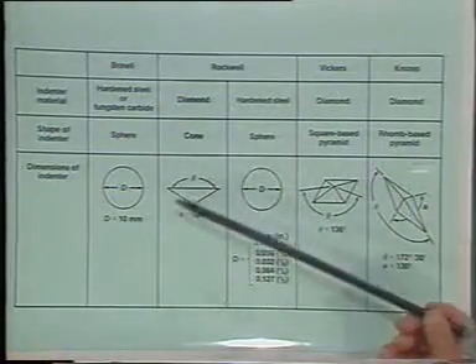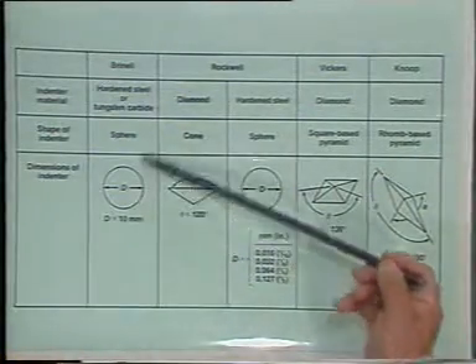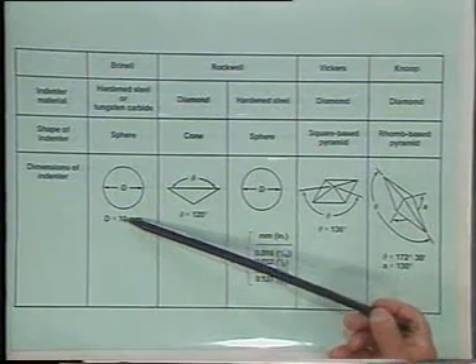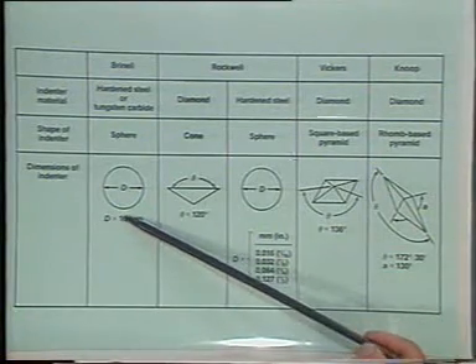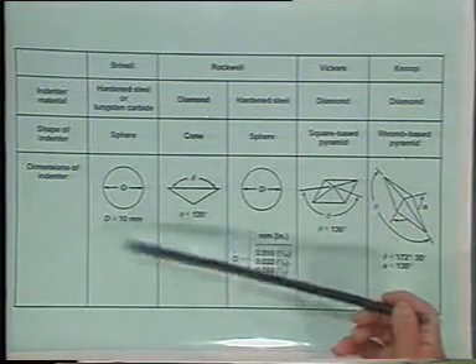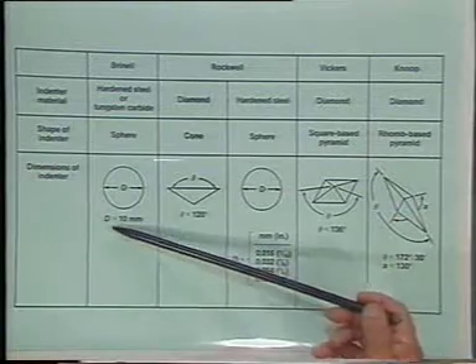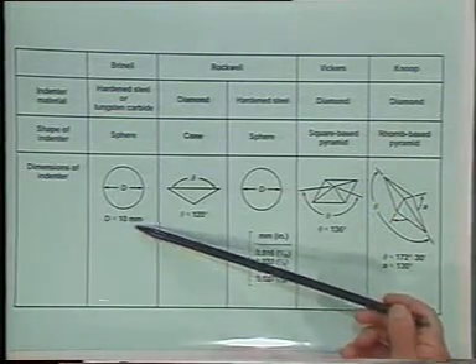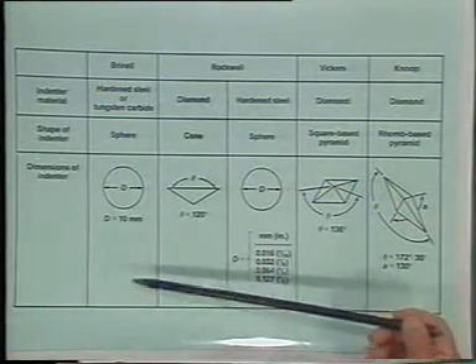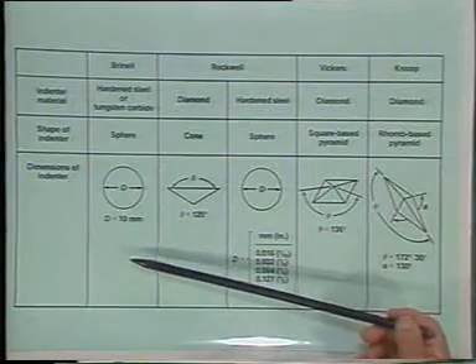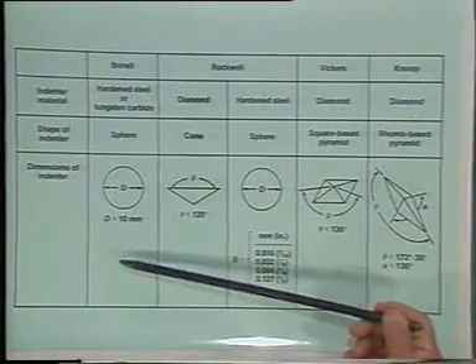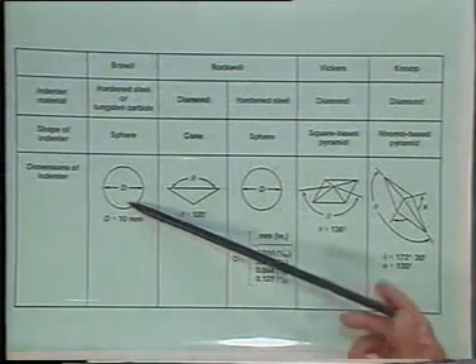If it is a piece of brass, a bronze, a non-ferrous material, we can run a Brinell test, but now we would, instead of loading it with a 3,000 kilogram load, we load it with a 500 kilogram load, and we can find a hardness, a relative number. It's just a relative number, but we could not necessarily equate that to the ultimate strength of the brass or bronzes. That table was just worked out for steel.